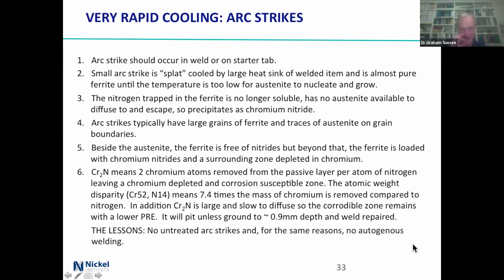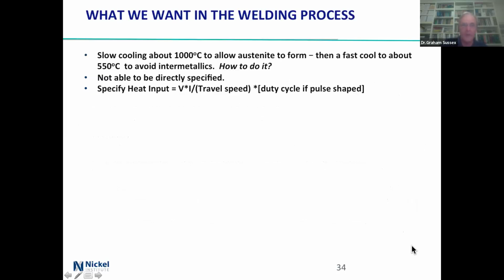Lessons: no untreated arc strikes, and for the same reason, no autogenous welding. Right. What do we want in a welding process? Slow cooling to about 1,000 degrees to allow the austenite to form, and then a fast cool to about 550 to avoid the intermetallics. Well, you can't exactly specify that, but you can say it.